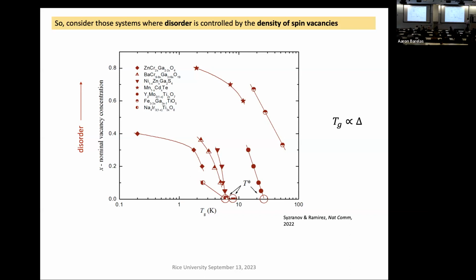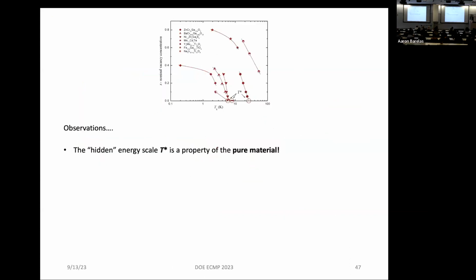And that energy scale is sort of geometrically between the Debye temperature and the lowest interaction energy in the system, the dipole interaction. But this is a feature of the pure system, and that's ultimately what we're interested in, because we're interested in pure behavior. Let's figure out the pure behavior first before the disordered behavior. So the observation is the hidden energy scale, we call it T star, a property of the pure material.